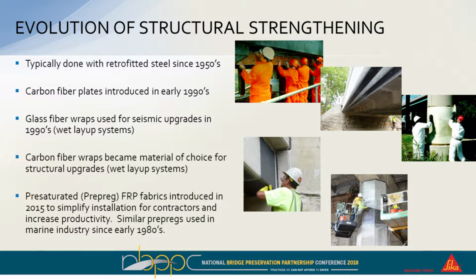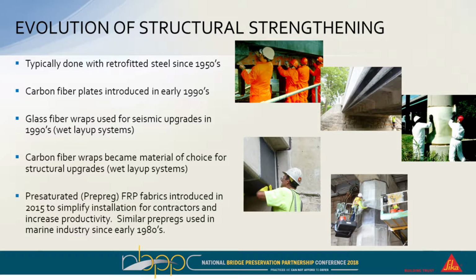This was replaced over time, but really in the early 1990s is when the use of carbon fiber and FRP materials first came to prominence, at least in terms of a commercial aspect. And here you can see some carbon fiber plates that were used for flexural strengthening back in the early 1990s. Then glass fiber wraps were used for a lot of seismic strengthening, also in the early 1990s, and Caltrans is one of the early proponents of this for replacing steel jacketing, again for seismic upgrades. Some of the early systems were done with what's known as a wet layup process. I'll show you in a few seconds what we mean by a wet layup.